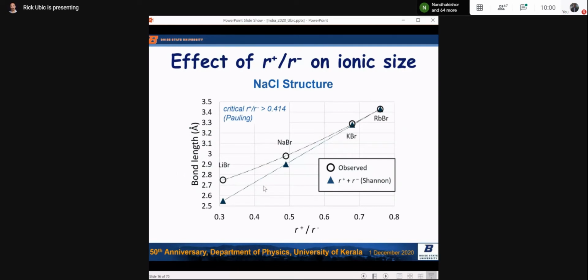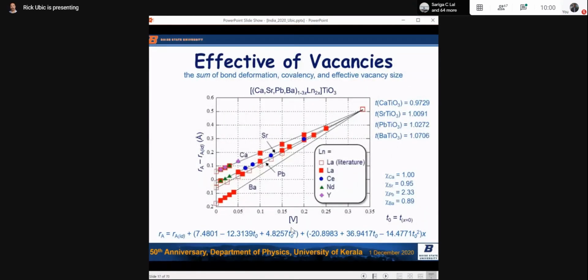And my student did this graphically for me here. So rubidium bromide up here, there's no discrepancy, and as you go down in the ratio, the discrepancy opens up quite a lot, right? So here Pauling would say the critical value for the radius ratio is 0.414, but it doesn't work in reality. Pauling's rules often don't work in reality. But the important thing here is that the size is a function of the ratio. And that's exactly what we're observing. And it shouldn't be new because this was published in a book from the 60s, right? So it's been known for a while. It's just often ignored, and sometimes people aren't aware of it.